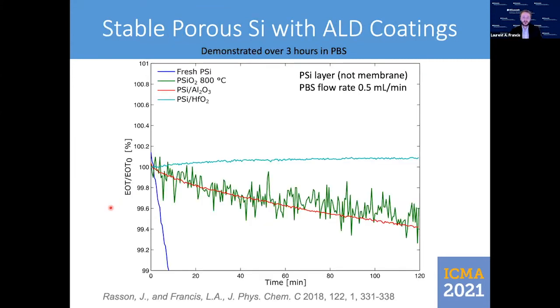There is another advantage from this coating. Here we have a comparison of different coatings by ALD on top of this porous material. And in the first case, when we use the freshly anodized silicon substrate, we have this blue curve showing how the signal is shifting due to the dissolution in the saline solution.